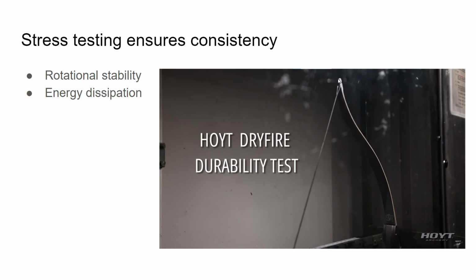This causes very high stresses in the limbs and can result in limb failure if they are not properly addressed and accounted for. Again, dry fire is a situation that should never be done on a recurve bow, but Hoyt does test this exact scenario to ensure that in case of accidents, the limbs are able to function just as well afterwards.